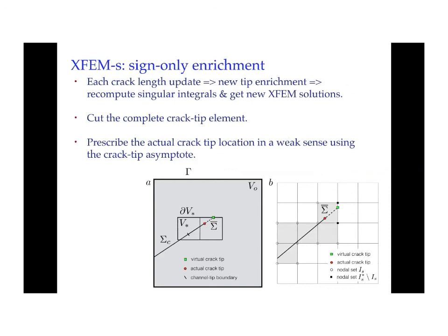So what we found is that if you use XFEM, you need to be cautious when you do non-planar fracture. So for the non-planar fracture in this work, we only use complete crack tip enrichment in order to correctly capture the crack path. So that's one part of the answer to your question.